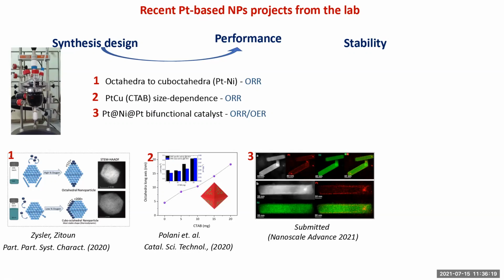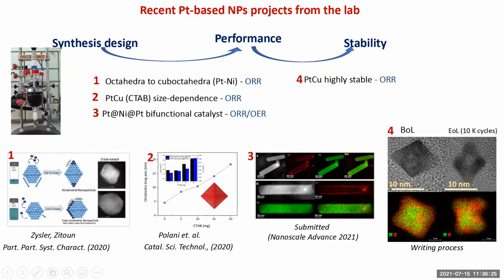Once we have a good material, that usually is platinum based with copper, we study the stability. We perform 10,000 cycles, even more, 20, 30, depending on the usual parameters that are compared all around the world. We study how the performance will be after, for example, 10,000 cycles.